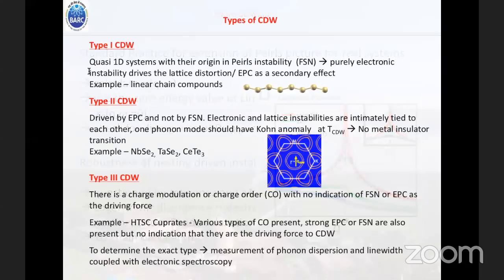One is a quasi-1D system where Fermi surface nesting drives the EPC, that is the electron-phonon coupling. Another is type 2 CDW, which is driven by electron-phonon coupling and not by Fermi surface nesting. And there is a type 3 CDW where there is a charge order present within the system, and there is no indication that FSN or EPC is the driving force for that charge order.